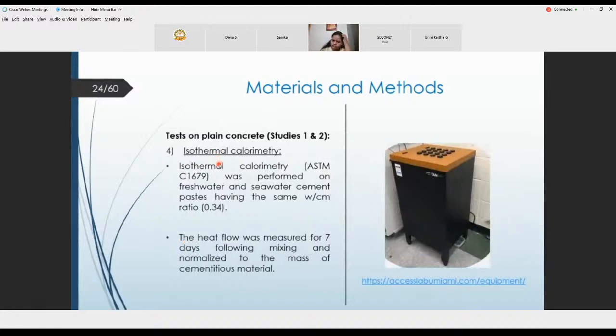We also conducted the isothermal calorimetry in studies 1 and 2. We also did the heat flow, measured 7 days following the mixing and normalized to the mass of the cementitious material.